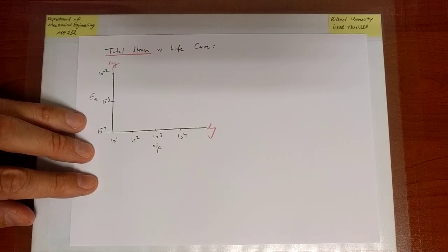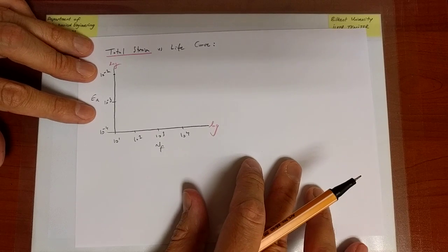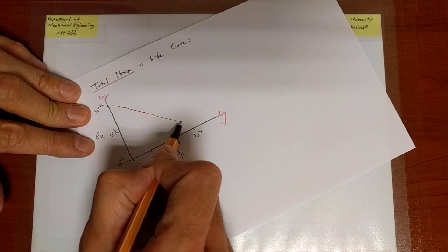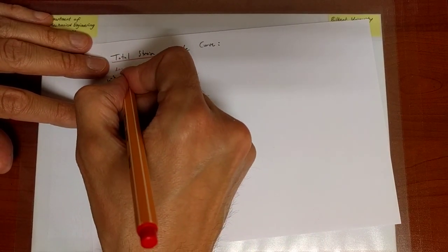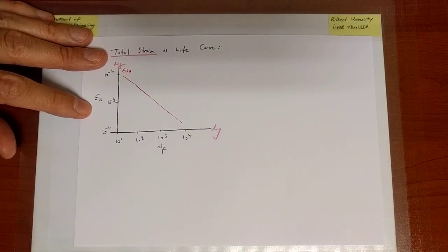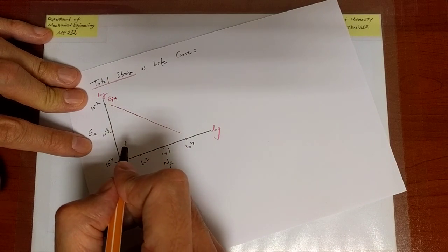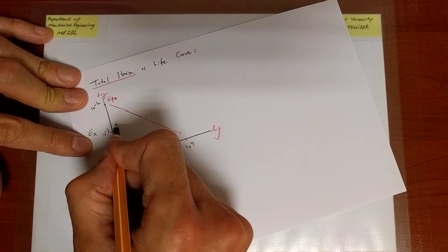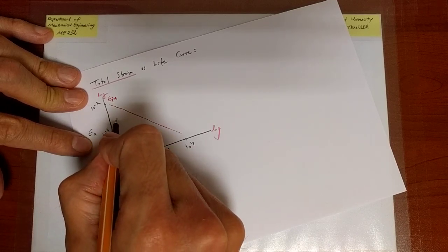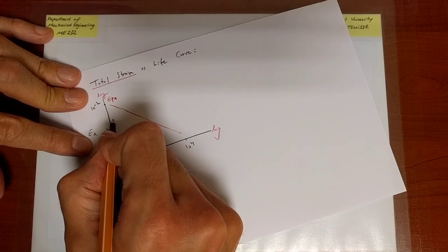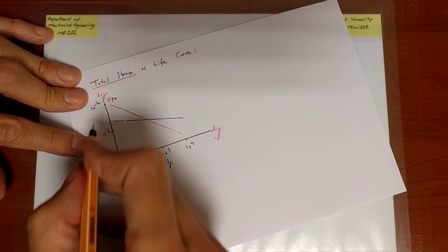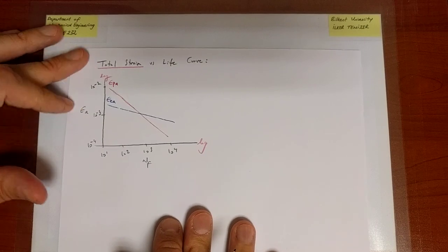And then we had generated two models. We saw that, first of all, the plastic strain seemed to fit on a line that looked like this. So this is associated with epsilon PA. On the other hand, the elastic strain also followed a straight line here with a smaller slope, it turns out. That was our observation essentially. And let's say that is the curve that we have for the elastic portion of the strain.